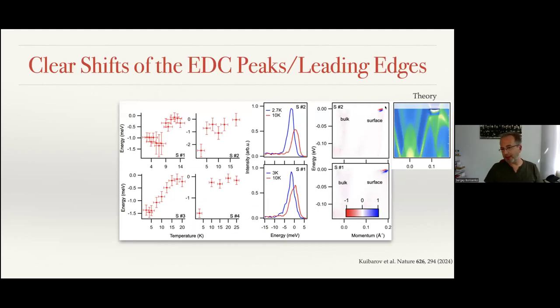So this is the kind of smoking gun experiment. You measure at low temperatures, you measure at higher temperature, and you see how the energy distribution curve shifts. This indicates strongly that there is an opening of a superconducting gap. And this is in the colors red, white, blue. This is a different spectrum above TC and below TC. And you clearly see that nothing happens with the bulk, but only the surface feature clearly shifts and the gap opens at the surface.